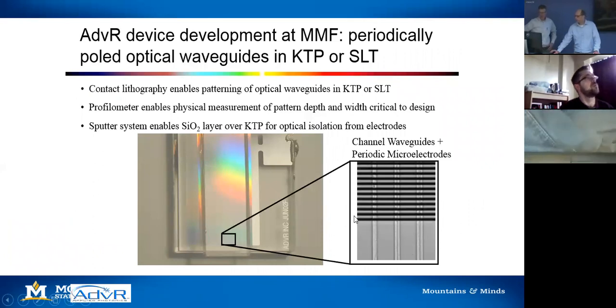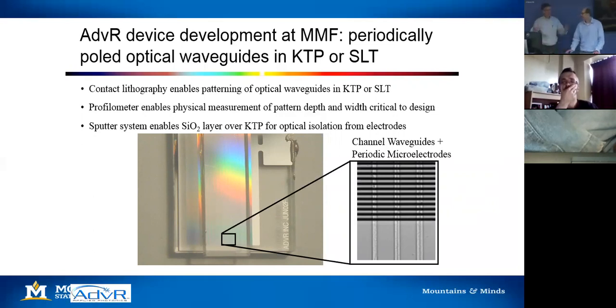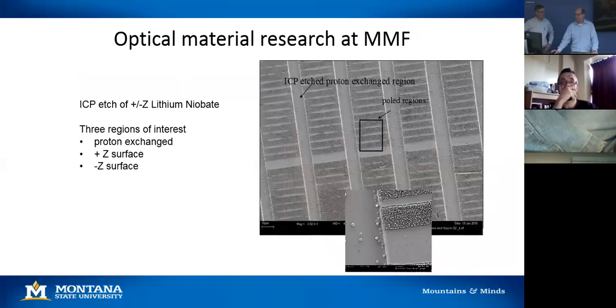Just here a quick example. Waveguides here, you have a mask pattern, and here they actually have a mask for poling. And so they actually switch the electric field. These are ferroelectric materials, and so they have a polarization direction. And that plays into, when you process these materials, what kind of structures you can get. It's also some of the challenge of working with these materials because they're pyroelectric. Yeah. So you put it on a hot plate and heat it up, and it's suddenly arcing. Yeah, and that does weird things to your photoresist. And it breaks, and these are expensive. So there are just some details with these ferroelectric materials.